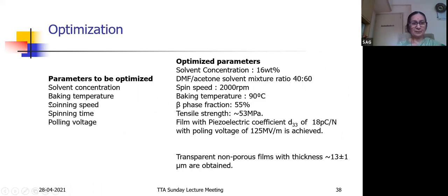These parameters we optimized: solvent concentration, baking temperature, spinning speed, spinning time, and the poling voltage. Poling voltage required is 125 megavolt per meter. Of course, this 1 meter we did not have. We had a sensor with few microns, so we had to go for lower voltages, and we had to purchase a power supply for that purpose, because current required is very small. It's a dielectric film, so current required is small, but the voltage is higher.